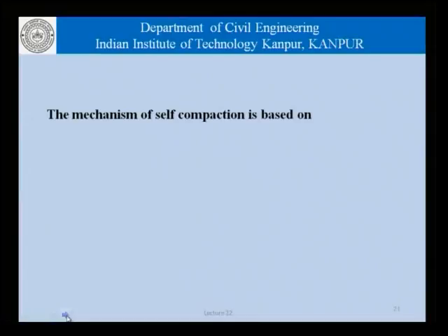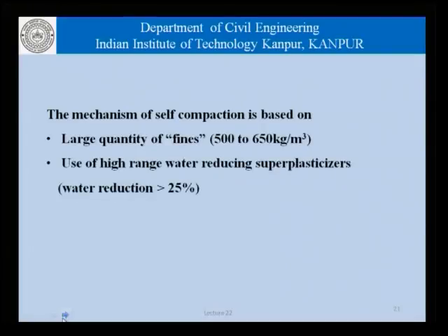Now, the mechanism of self compaction in self consolidating concrete is based on the large quantity of fines of the order of about 500 to 650 kgs a cubic meter, the use of high range water reducing superplasticizers in the range of more than 25% of water reduction, and viscosity modifying admixtures. So, it is these three principal factors or a combination of these factors which helps us obtain self compactability in concrete. So, when we are talking of a large amount of fines, we can imagine that if we are looking at 500 to 650 kgs per cubic meter of fines, this is not including the fine aggregate. This is really the fines in the sense of cement and particles which are of similar size.